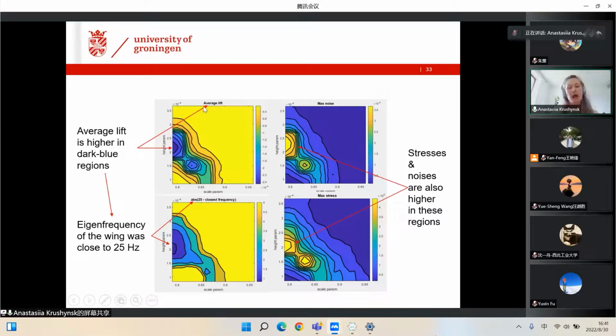And in the same way, we construct the maps for our key characteristics: for lift, for noise, and for stress, for the same parameters. And you can see that as soon as the eigenfrequency is close to the excitation frequency, the lift has maximum values. So here we should have a look at the magnitudes, not the sign.